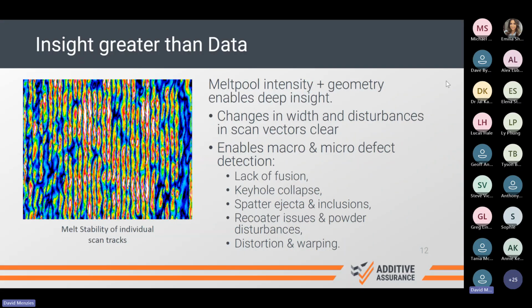So the common defects in laser powder bed fusion that we're targeting are lack of fusion, which creates pores, keyhole collapse, and spatter, which is obviously a problem when you have balling occurring across your build. We can also see more macro geometrical issues, such as those occurring in the powder layer from the recoater, or whether the part itself is having any level of distortion or warping occurring.